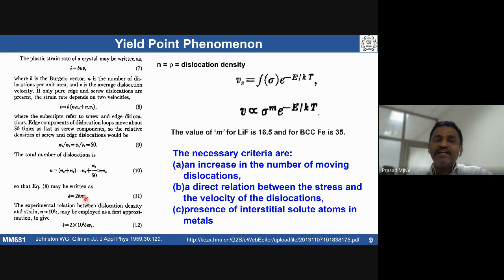Your strain rate locally, inside the representative volume, is increasing. Though I'm deforming the material at a particular strain rate, my internal strain rate at a given representative volume is locally increasing, until maximum stress, the upper yield point.